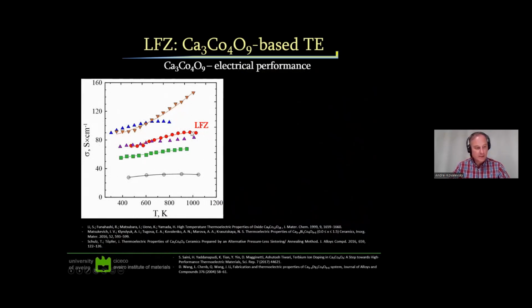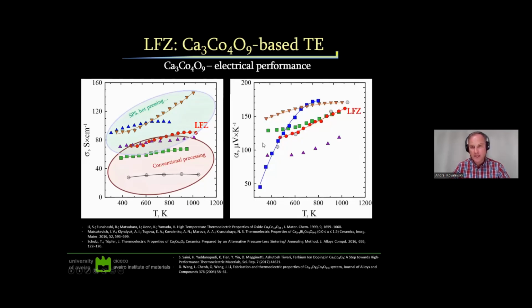So the red curve here corresponds to laser grown materials, and here I've put some literature data. Basically, in terms of electrical conductivity, we're somewhere on the borderline between conventional processing and application of some specific methods like spark plasma sintering or hot pressing. So the results are quite good, but still not something really outstanding.